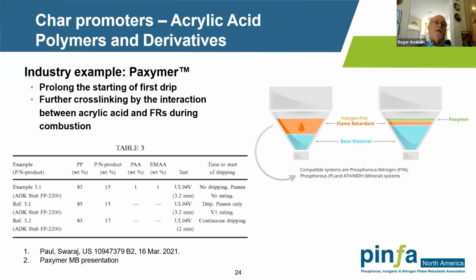Here's a char former. This is a commercially available acrylic acid polymer and derivatives, and you can see some of the examples. You can then refer to this company called Paxymer, and their materials, Paxymer, the trademark, and you can see their reference to their patents and to their presentation. Basically, it prolongs the starting of the first drip. And by this cross-linking mechanism between the acrylic acid and the flame retardants used, it tends to mitigate dripping, reducing the amount of dripping. So it works as both a drip suppressant and synergist with non-halogen flame retardants. Typically, they first started out in the polyolefins, and I know they've been working on developing some systems that work in the engineering polymers as well. So this is a good example of an ionomer used as a drip suppressant. Next slide.